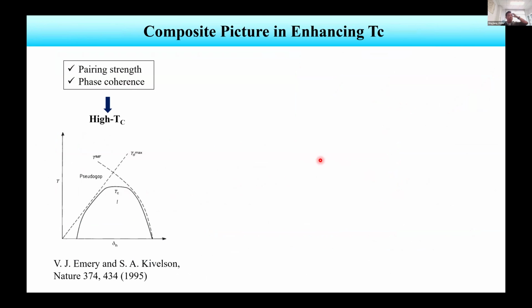Then, to understand why the TC is high in this bismuth 2223, we need to understand that superconductivity is usually realized by going through two steps. The first step is to form the Cooper pairs. The second step is that the Cooper pairs form a coherent state. The pairing process and the phase coherence process usually occur at the same temperature in conventional superconductors, but in some unconventional superconductors they may happen at different temperatures.